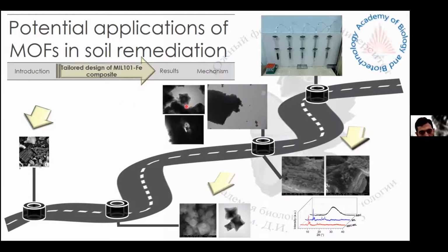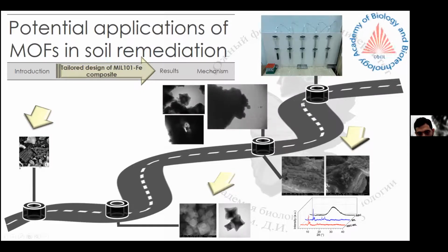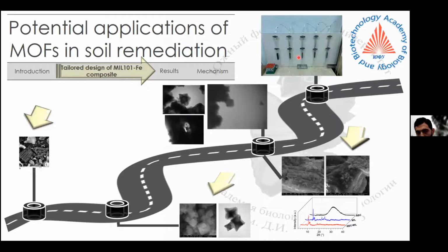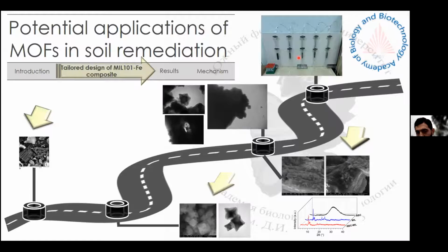Here is the TEM photo. You can see the biochar has been used as a host to grow the MIL on top of the edge, and here you can see one of the pores that the biochar has, and the metal organic framework has grown inside. And here is a short TEM video of the big biochar particle and the MIL. You can see that they are growing on the edge of this particle. And the last one is a small leaching column that we designed specifically to see the performance of our composite.